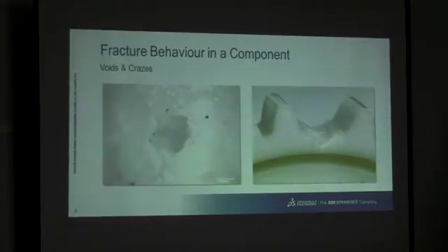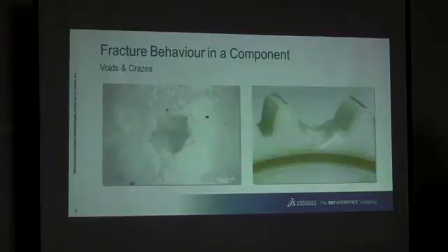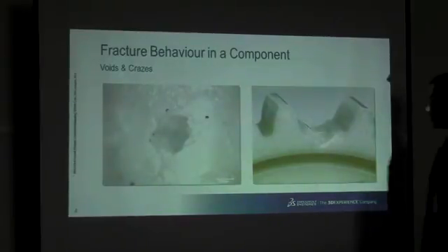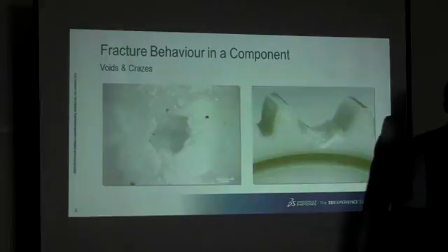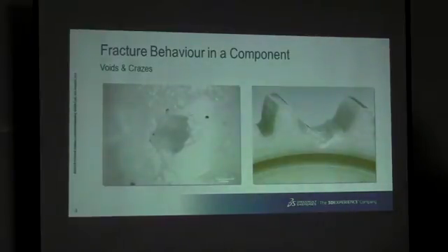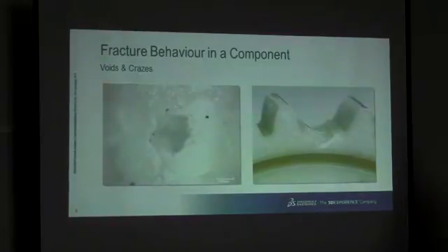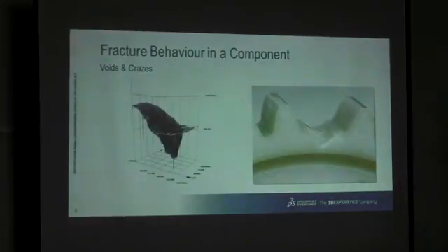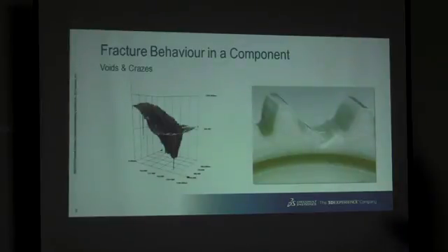So, in a component then, this is not a very pretty picture on the left-hand side. This is a void. This is a void that we found after we looked at the fractured component, so we couldn't have seen it from the outside. We decided, okay, let's put it under a scanner, and see what this looks like. That's quite a nice little block. It's quite deep. And this is not something you would detect unless you're doing CT at the time that you're testing, or MRI for that matter. We tried CT, but it was a bit too difficult to assess during the sample loading, and also became hideously expensive. We ran out of funding.